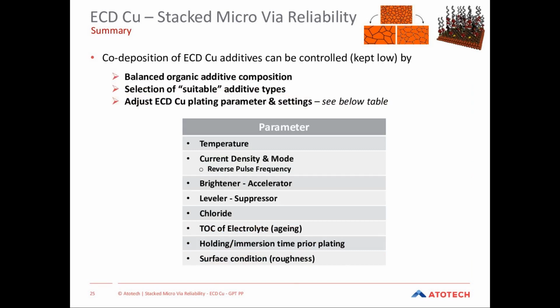Finally, as I said already, there are several parameters which are important. For sure, it starts everything with selecting the right organic additives and to combine them in a way that they are balanced and no additive dominates during the adsorption at the interface nucleation of electrolytic copper processes. But of course, parameters like temperature, current density also are very important to adjust in this regard. So we found, for example, with high reverse pulse frequencies, that we can prevent additive adsorption at the beginning of the plating process very much. That means at the end, in reverse pulse plating application, we found also a higher reliability of the stacked buildups.